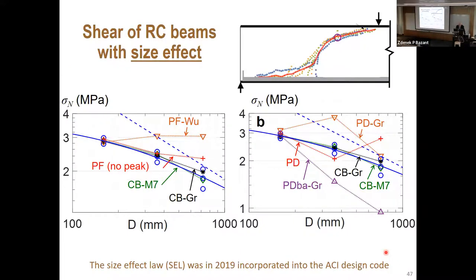Another test, still shear effect. There is a size effect here. It actually beautifully follows the size effect law which I showed. The size effect law was, after long arguments, put into the ACI code. Every design must consider it for beam shear, also for slab shear, and for footings. So you see this curve of the size effect formula is followed well by the test data. These are for different sizes of the beams.